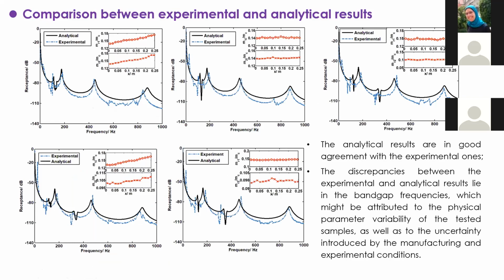This is a comparison between the measured results and the analytical results. These sub-figures show the distributions of resonant mass, the change of the resonant mass along the beam. We manufactured 5 different samples. Basically, we can see that the analytical results are generally in good agreement with the experimental ones. There are indeed some discrepancies, mainly, for example, in the frequency of the band gaps.